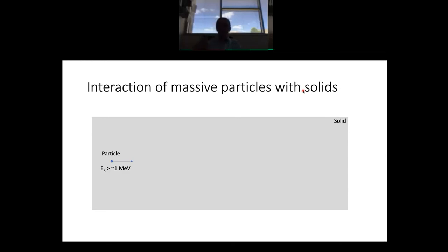Photon radiation, radiation by gamma particles and things like that is obviously important, very different from radiation with massive particles. So I'm not going to touch it. I'm just going to focus on the massive particles. So let's say that I have a massive particle, and this could be a neutron or an ion or even an electron, and it is impinged upon a solid. It's now flying through the solid at high velocity with its high energy. Okay, so this gray thing here is the solid.